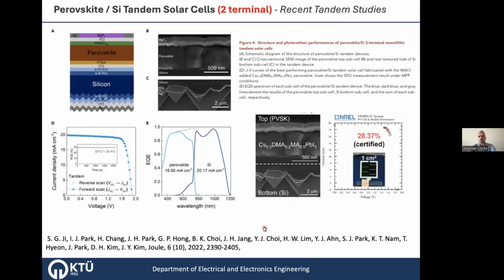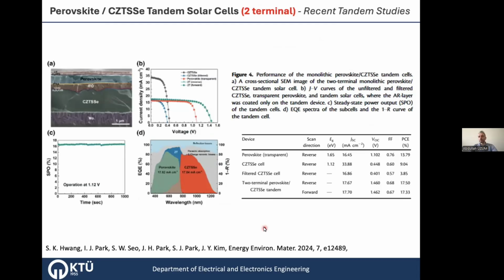But of course, it doesn't have to be silicon all the time. The bottom cell can be changed. There is a lot of research with other structures, other cell types. For example, in this one, CZTS selenide as the bottom cell, with its band gap, and the transparent perovskite is 1.68, 1.65 here, electron volts band gap.